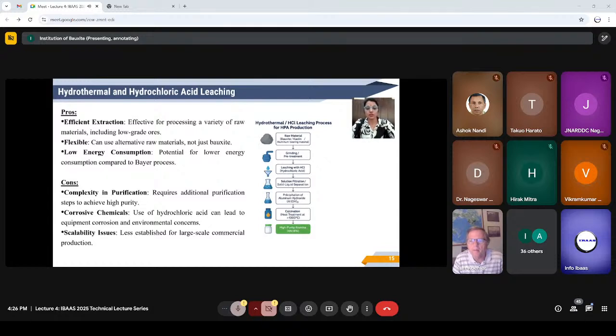The solution undergoes purification using techniques like solvent extraction or ion exchange to remove trace impurities such as iron, titanium, silica, etc. So once it is purified, aluminium hydroxide is precipitated from the solution. And this step is typically achieved by adjusting the pH or adding a precipitating agent. Finally, the precipitated aluminium hydroxide is calcined at high temperature, usually above 1000 degrees Celsius, to obtain the high purity alumina.